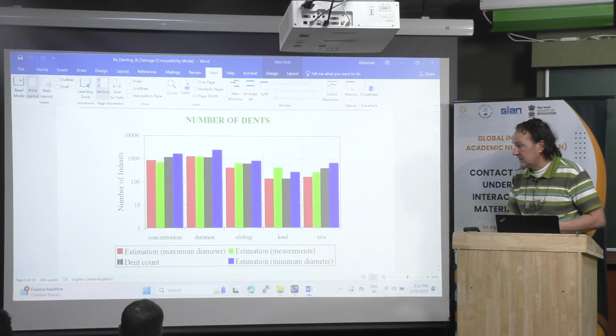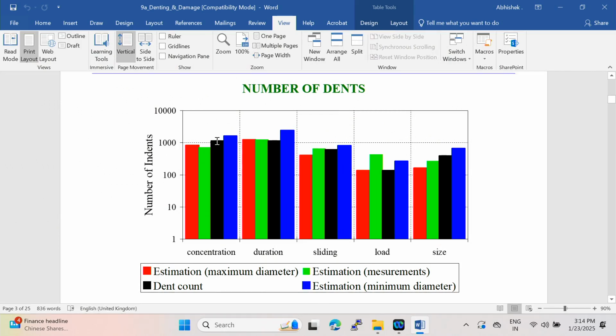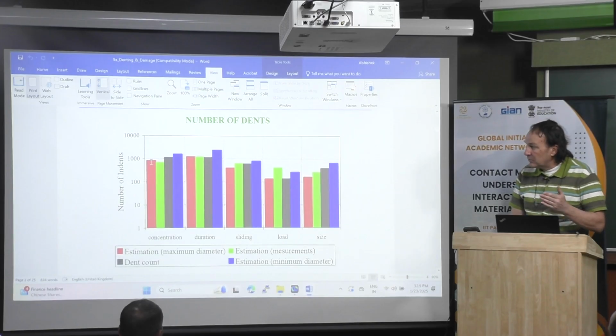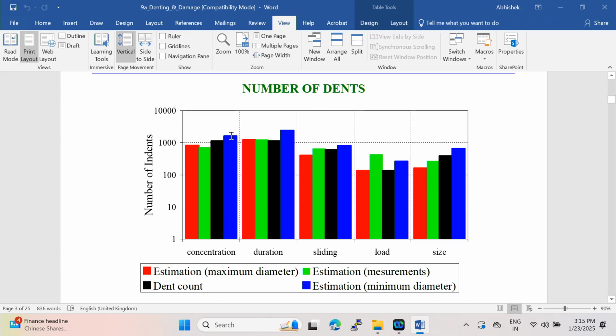Then in black here, this is an example of measurement. This is the number of dents that we have counted, about 1,000, a little more than 1,000. This is a log scale, okay. Now, for example, if the class of particle is between 20 to 32 micrometers, and you know how many milligrams you put in the oil, we can know that for the largest size of particles, you should have something which is, for example, 900 particles. If you have smaller particles, you will have more particles. Then the estimation will be this one, a little more than 1,000.